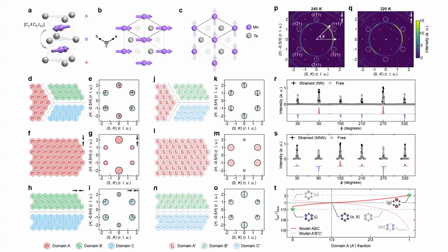You don't have to know the details, but we have actually done the experiment for strain along both the nearest neighbor and the next nearest neighbor direction. After very careful analysis, our basic conclusion is that the magnetic structure is conclusively M prime M prime M, and this is independent of which direction we apply the unilateral pressure. Basically, the magnetic structure is fixed relative to the underlying lattice, regardless of which direction you apply the strain, and the magnetic space group is conclusively M prime M prime M. That suggests that the anomalous Hall effect seen with transport measurement is really due to the fact that the system is an altermagnet.